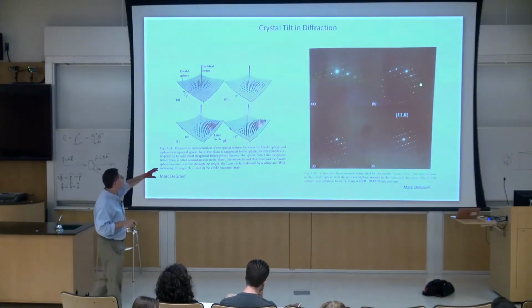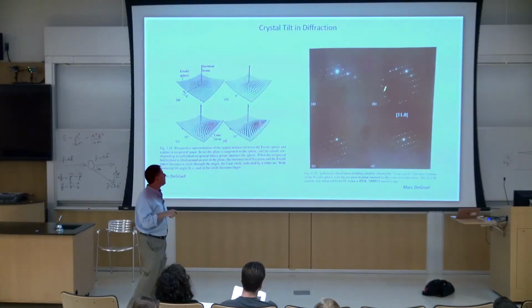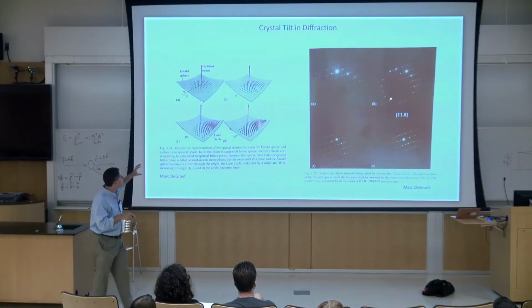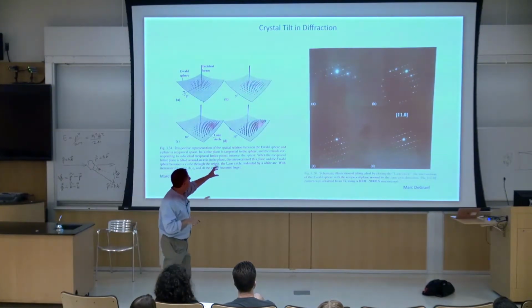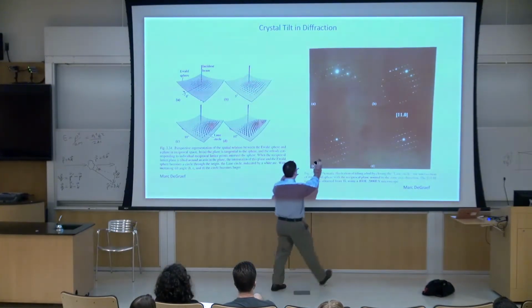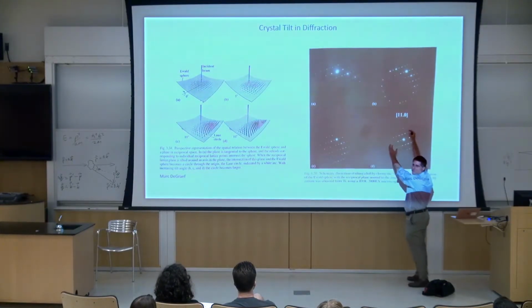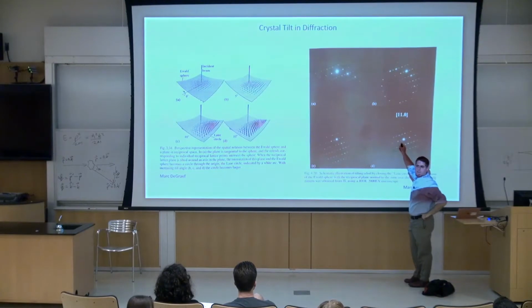And often what happens is, the way to think about your tilting of the diffraction pattern is remember that this spot, the unscattered beam, is always pinned. And then I'm trying to tilt by moving the Ewald sphere so that it ends up going shift, shift, shift, shift, shift. And now it's centered around the central spot. Now I'm on the zone axis.